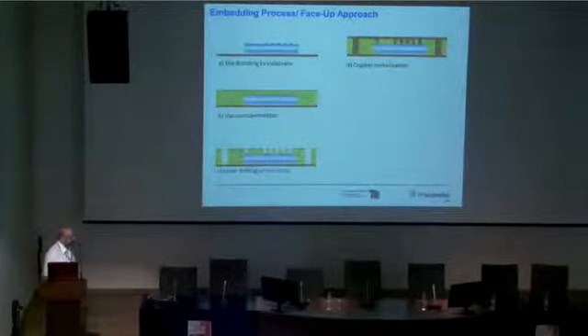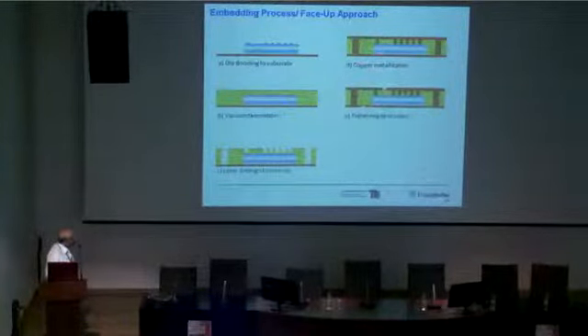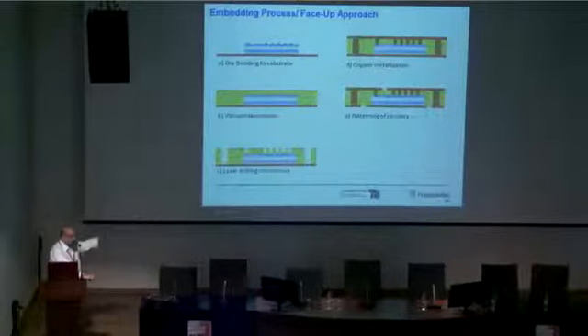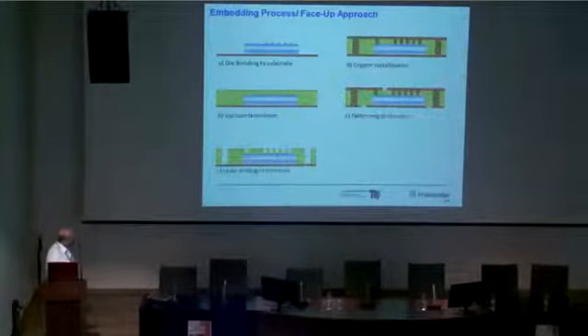Then the next step, which happened very fast, was the opening of the micro vias on the chip and the copper pads. You use a UV or a CO2 laser. Here I have to bring to your attention that the UV is quite aggressive, so you use a UV laser to open the copper and a CO2 laser to open the epoxy resin on top of the copper pad. Then you do copper metallization. By metallizing the whole structure, you deposit about 5 or 7 micron copper all over the surface, on the top and the bottom, and then you do a typical lithography process to structure the top and the bottom of the package.